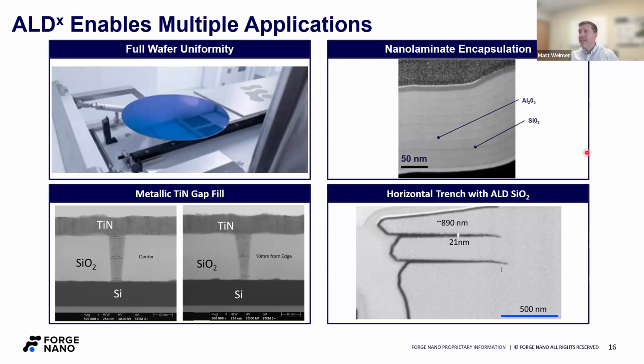Nanolaminate encapsulation, that's always the headline application. And we can do that quite regularly, quite easily in our tool. Typically, the tools are outfitted with 3 metal precursors, so you could even make a ternary oxide if you felt so inclined. Also, people always ask us, well, this faster ALD, is it still ALD?